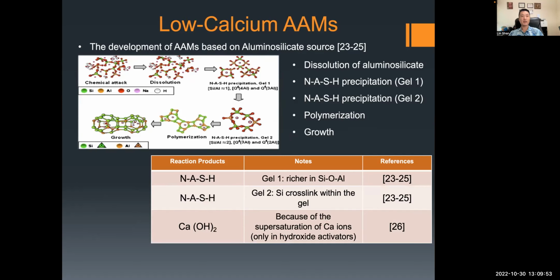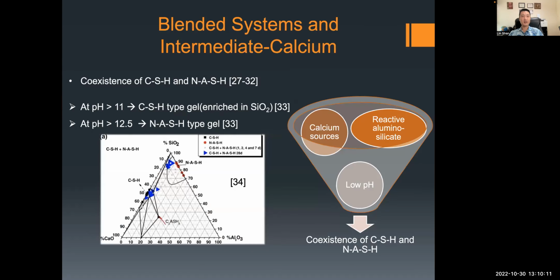And for low calcium AAMs, we could have the famous geopolymer. We also call that N-A-S-H. We have two types of N-A-S-H, gel 1 and gel 2, plus we could have calcium hydroxide. And then for blended systems and intermediate calcium, we could have coexistence of C-S-H and N-A-S-H. And also depending on the pH level, we could have different types of reaction products.